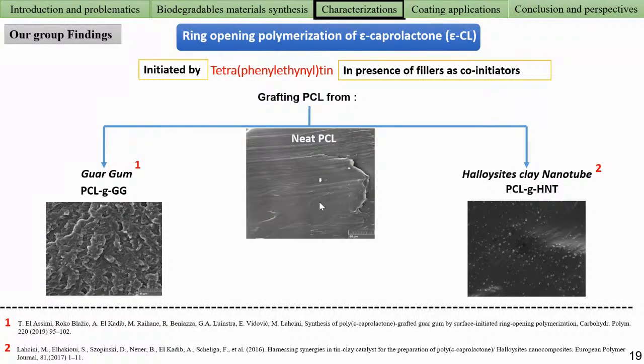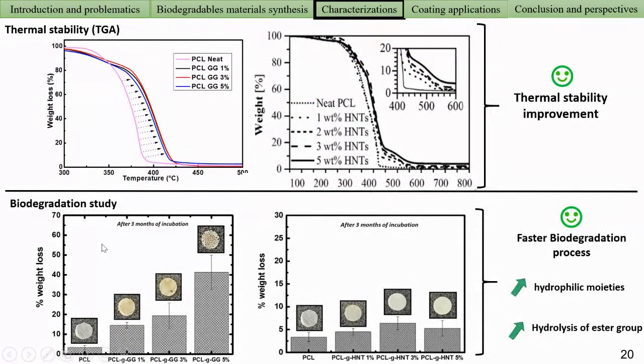The image shows us that we have really good dispersion of the fillers in the matrix. This is with halloysite nanotubes and even with guar-gum. And the incorporation of the fillers with the polymer increases the thermal stability of the nanocomposite. As you can see, even with guar-gum or with halloysite nanotubes, we really improve the thermal stability of the materials.